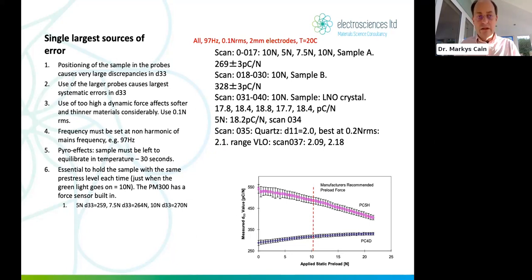It seems the single largest source of error in doing this measurement is positioning the samples between the probes, making sure that they are concentric and aligned. This causes really large discrepancies in measured d33. Soft materials are different to hard materials, and different geometries are affected in different ways. The larger probes, in this case, cause the largest systematic errors in d33. You might have thought that a large hemispherical domed electrode would be ideal because it seems more stable than using a point or a small diameter ball electrode. But indeed, the effect is the opposite. It's these larger probes that cause the largest systematic errors. It seems alignment between these large electrodes or flat electrodes causes the biggest issues, and there's another issue with regards to flat electrodes I will come to.